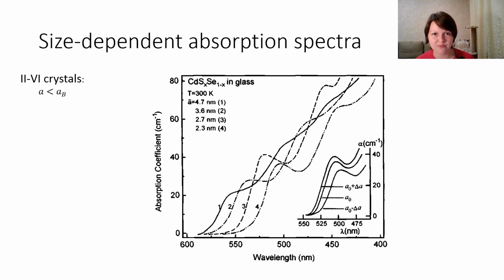So it means that the quantum size effect can help us to create technology for commercial uses. To synthesize 4 different cutoff color filters, we can use only one chemical composition of the batch, but 4 different heat treatment regimes. This is how quantum mechanics helps to solve different technological problems.